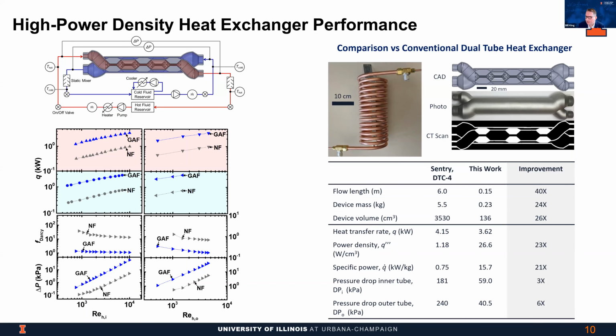So our device has 40 times shorter flow length, 24 times lower mass, 26 times lower volume. We tested these devices at approximately the same heat transfer rates, but at these rates listed, the power density is about 23 times higher for our device, specific power 20 times higher. The pressure drop is 3 to 6 times improved as well. So we were really able to meaningfully improve the performance of a heat transfer application compared to what is done today using these 3D geometries.